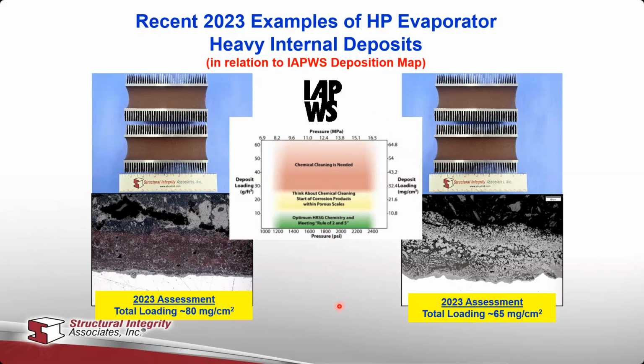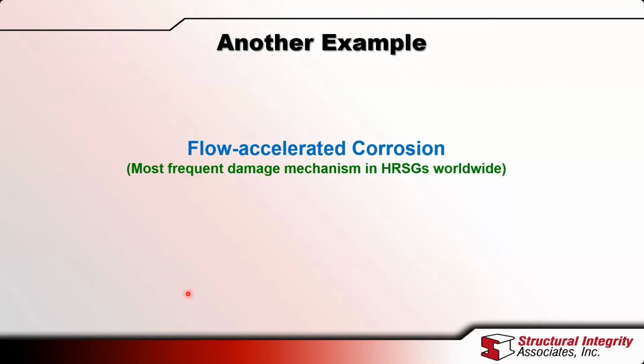So the idea is to take these samples at regular intervals so you can make sure that the deposits are not building up on the internal surface of the tubes. So that was the first example. The second example is flow accelerated corrosion, which, as I mentioned before, is the most frequent damage mechanism in HRSGs worldwide, and we still see many of these every year.